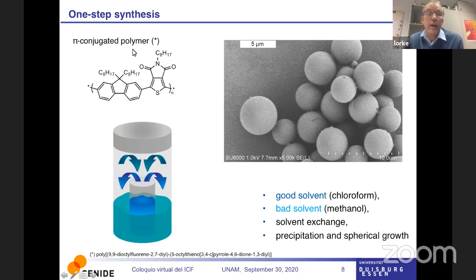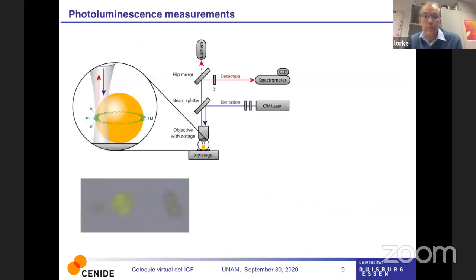And they have chosen this polymer in a way that it doesn't form crystals. And that's very important because crystals will never give you a perfect sphere. But we want perfect spheres, and they were able to get these perfect spheres. So they had to be choosy with this polymer. And this polymer is everything. It is the dye, it is the dielectric, and it is what makes these spheres.